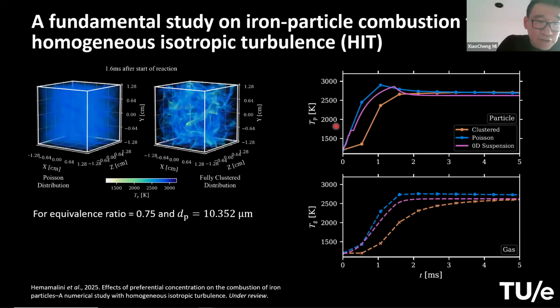You can see here on the top is the particle temperature as a function of time. There are three curves. The blue one is the Poisson or random distribution, and the purple one is the 0D model, which just assumes that all the particles react in the same way in this constant volume box. And the orange one is the temperature history of the clustered case. The particles start to burn after the clusters form. So you can see indeed this clustered particle distribution has a significantly longer burn time. Similarly, it can be seen in the gas temperature history, shown in this figure at the bottom.